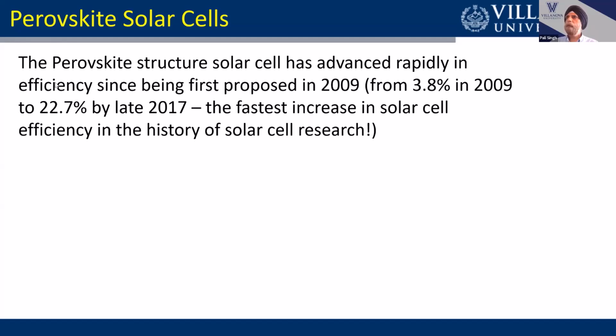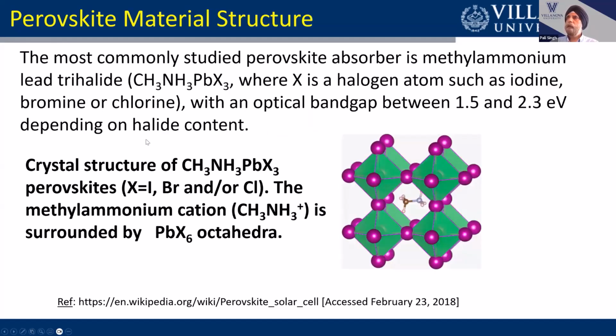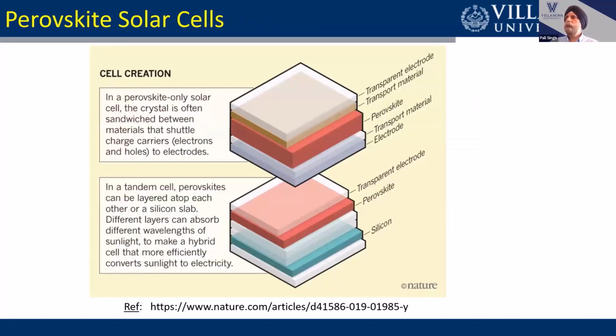So that's why all the buzz is around these materials. The most commonly studied perovskite is methylammonium lead trihalide. And I won't go into the details of the crystal structure here, but you can see that it has this sort of octahedral structure. So perovskite solar cells basically look like this. So this is a transparent electrode, then a transparent material, then the perovskite material, another transparent material, and then the electrode. So we have an electrode at the top and the back. This is the transparent electrode, so light comes through it, but it also is electrically conducting, so we can make a contact to the bottom and top of the cell and get current and voltage out of the cell. So this is a perovskite-only structure.